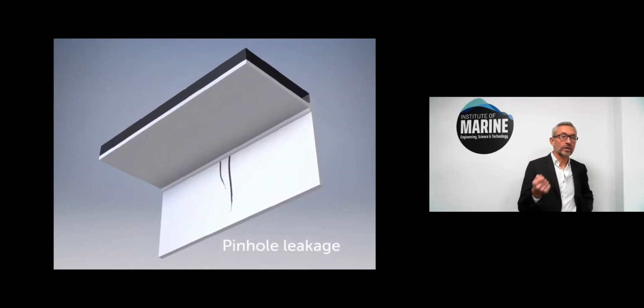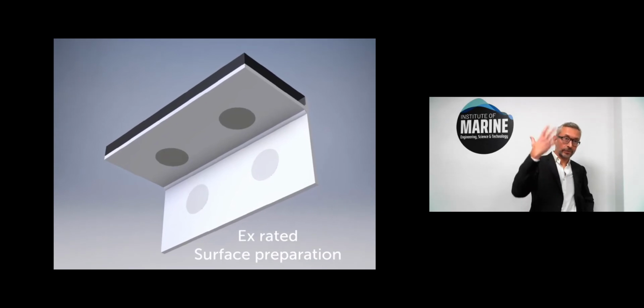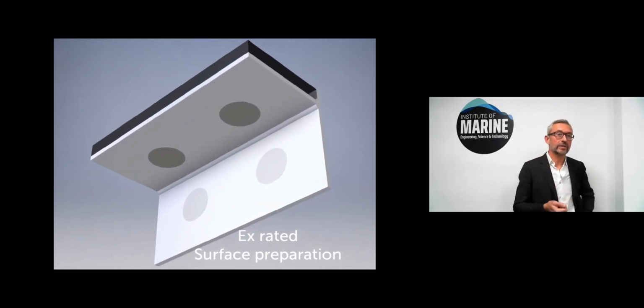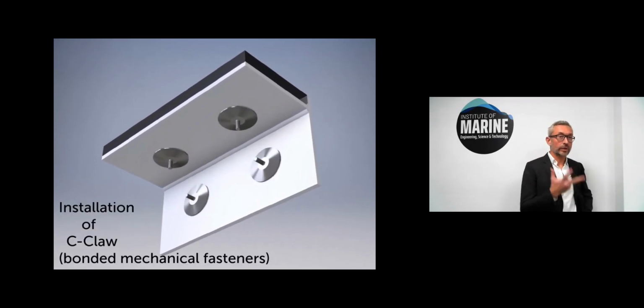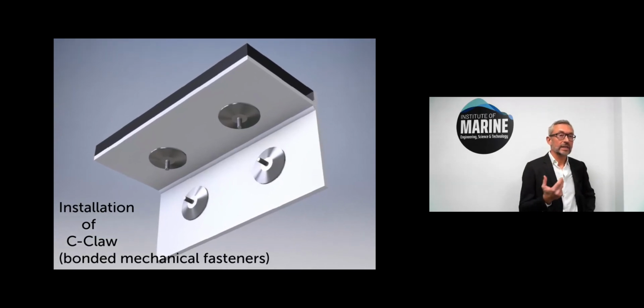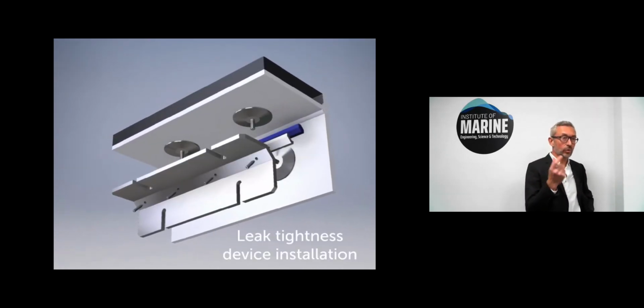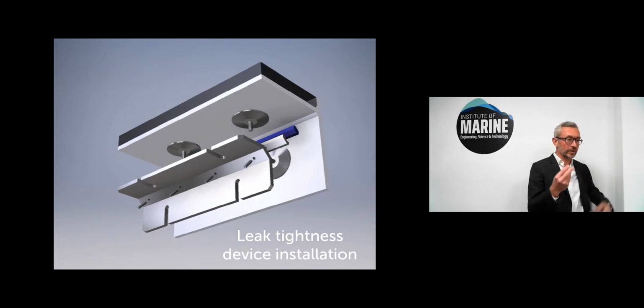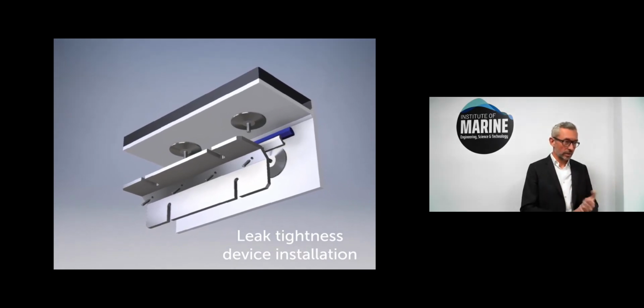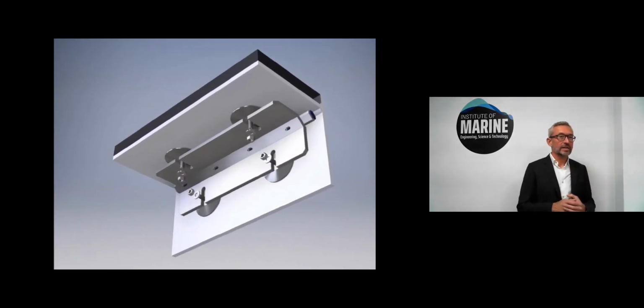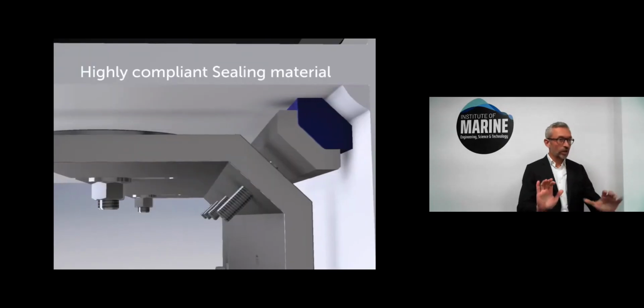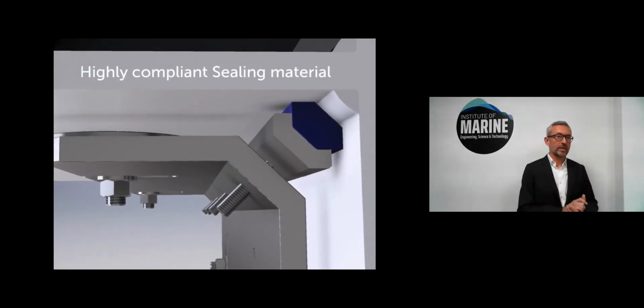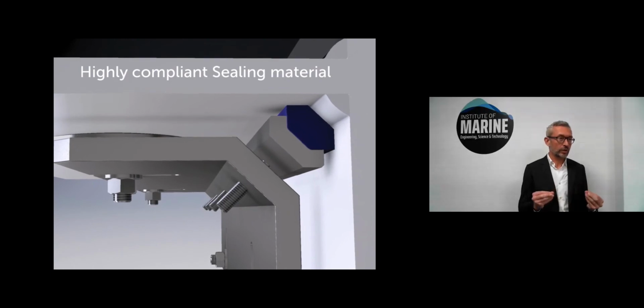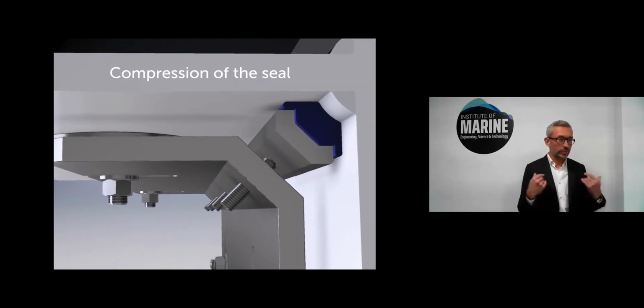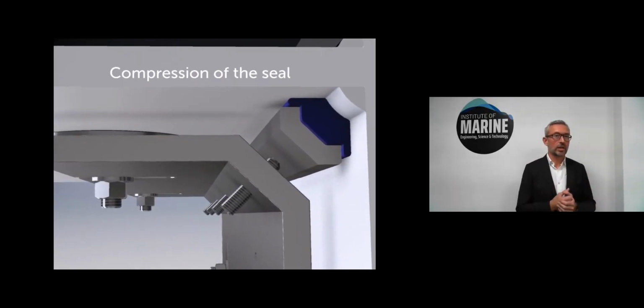So here there is a weldment, you have a porosity, you have a crude oil tank at the top, and the oil is leaking. So what we do, we install 4 anchoring points, and then we have a device that will have a blue seal, a fluorosilicone, a very durable material in contact with hydrocarbon, that we will force onto the porosity. And here we develop contact pressure which is sufficiently high to stop any leakage.